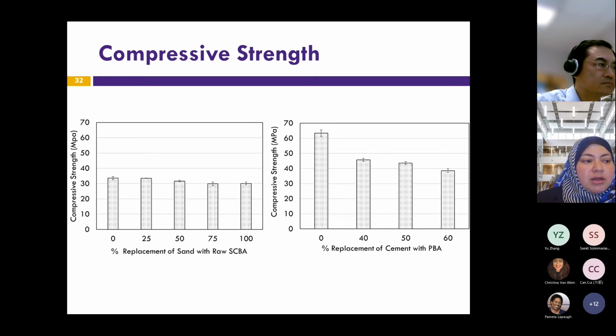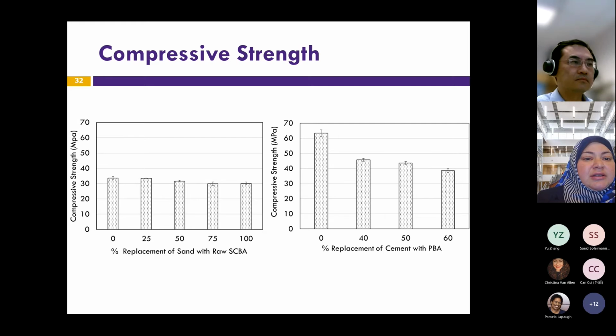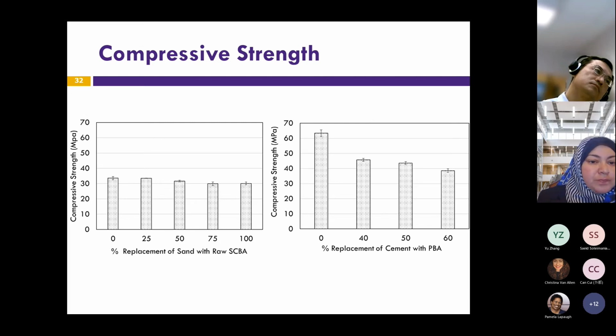Although when we did the test to identify the strength activity index, and when we did the SEM, we saw amorphous silica, which indicates that there is pozzolanic activities. We believe that the early strength is going to be lower, but as you leave it over time, the strength will increase. So we expect these numbers to increase over time.